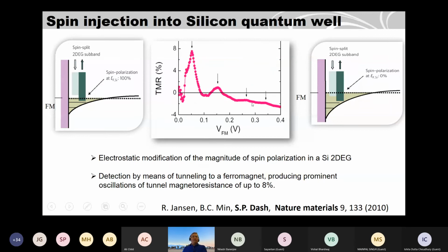That previous measurement was with bulk silicon. Also, you can make quantum wells of silicon. You can use a ferromagnet, then a tunnel barrier, then create a silicon quantum well by using some low work function material at the other side. So the band, instead of bending up, goes down, and you create these quantum well states. What we did here was apply a perpendicular magnetic field to create a spin split band in the silicon 2-DEG. So you have a ferromagnet here and a spin split 2-DEG band, and you can do a tunneling experiment in this.